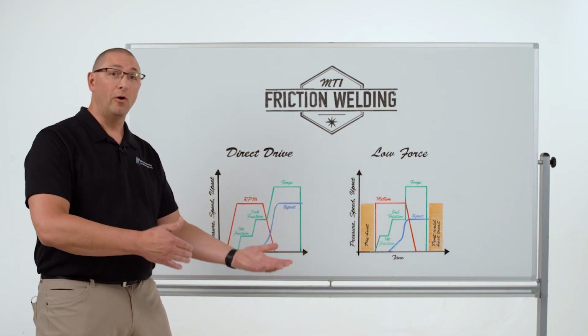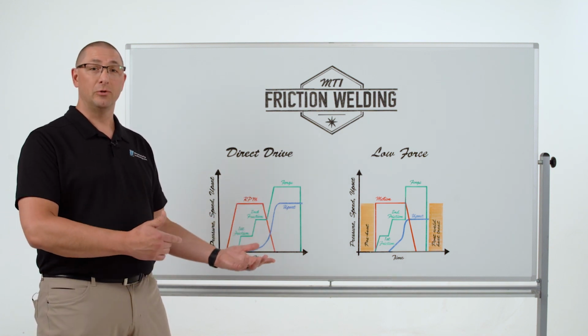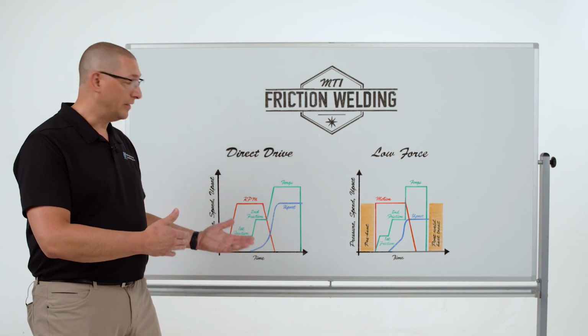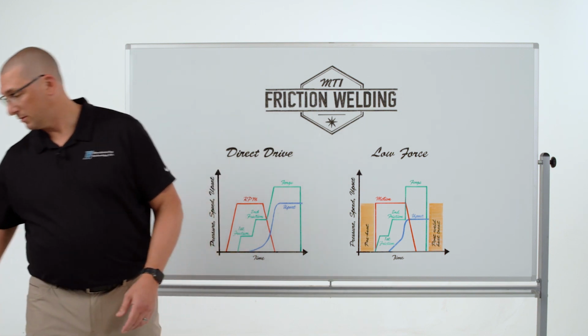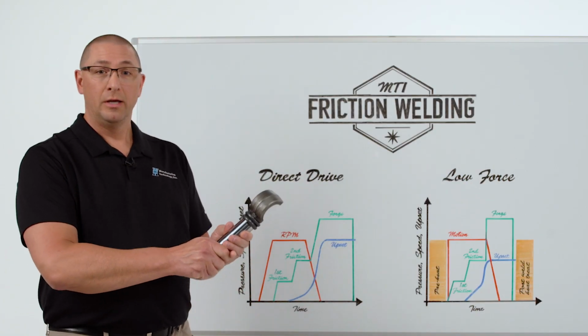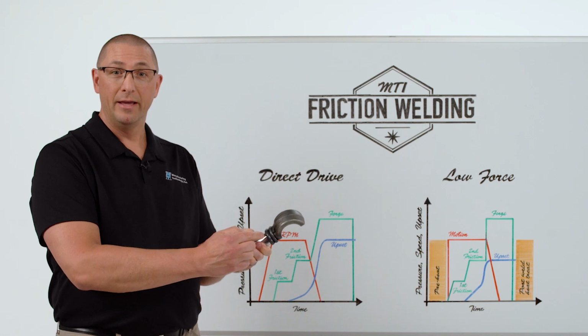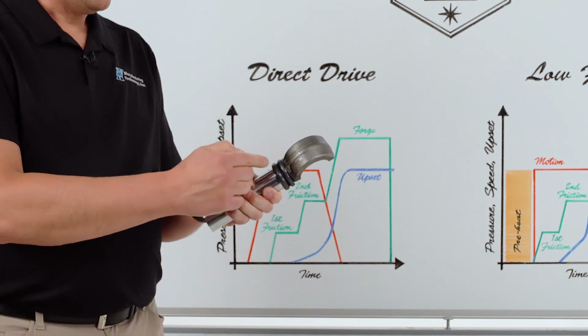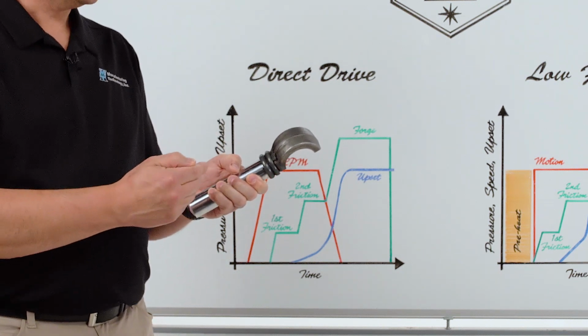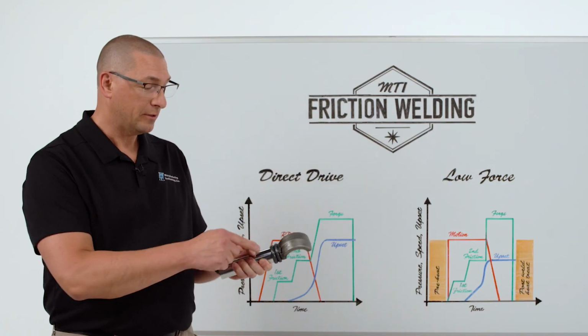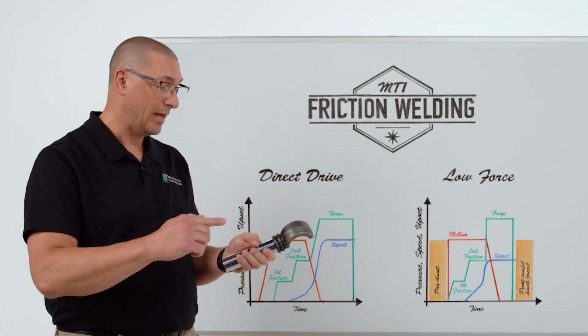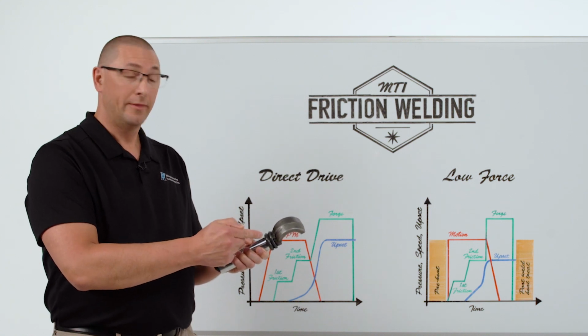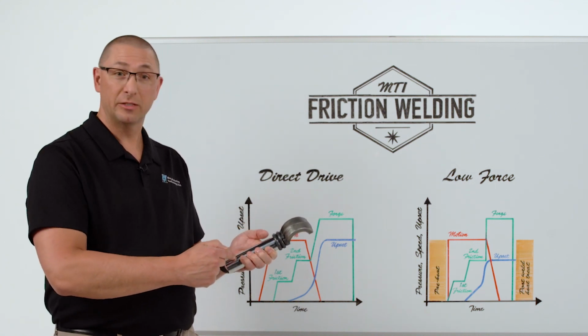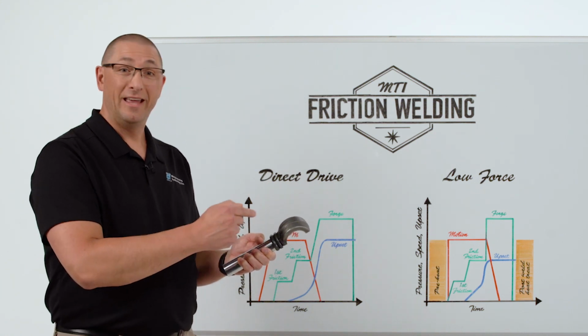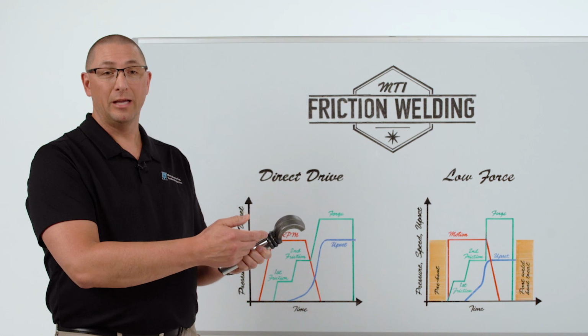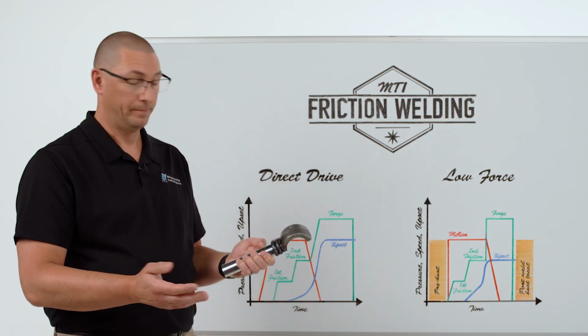But at that point, because of all the upset we created in second friction, we have to do a post-weld machining of the flash. And this two-axis machining is a very difficult process. As you look at a traditional hydraulic cylinder rod, the first thing that comes to your eye is this large amount of upset. So this flash formation has to be removed in a two-axis CNC style turning operation. And it's difficult because sometimes you have some of these little stringers that are off to the side. You have to make sure that you don't create a ring that breaks free from the rest of the flash and will then possibly scratch the pre-chrome rod. And this is a tremendous amount of cycle time. Many times it's often as long as the welding process itself.